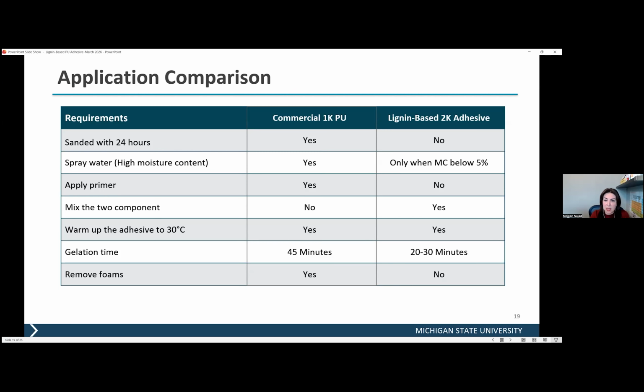The difference is that for one component adhesives, there is no mixing requirement. But for our adhesives, because it's a two component, they should have a mixer at the beginning to mix the two components together. The recommendation is that, usually in winter time especially, you need to warm it up slightly above room temperature to 30 degrees C. This also helps our lignin-based adhesives, because as I showed, it's going to drop the viscosity and make it easier to spray.